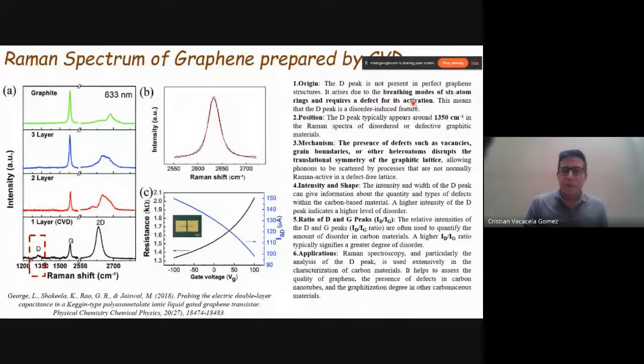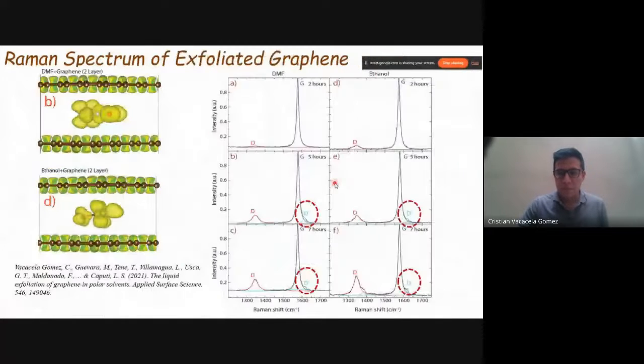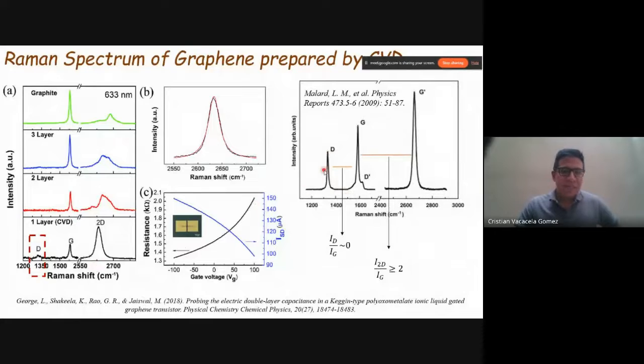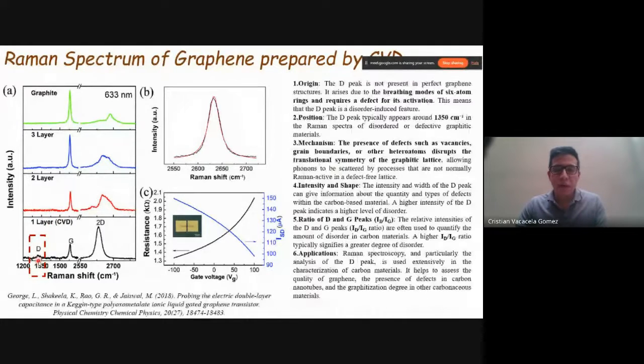So coming back, what is the meaning of this? In simple words, the presence of the D band can be attributed to the effects induced after the preparation process. You can see here, for example, using chemical vapor deposition, you have an intense D band. What does that mean? Here, this is a single layer of graphene with a high density of defects, and here is a single layer of graphene with a low density of defects.